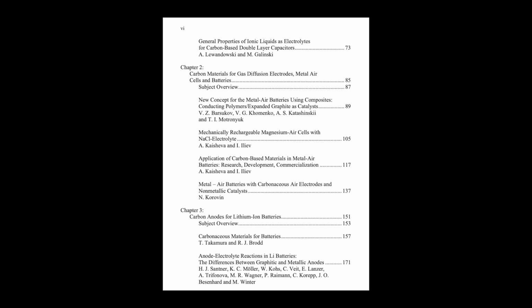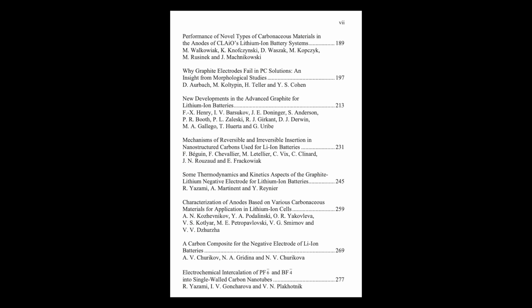The source also got really fundamental, looking at the actual steps of lithium going into graphite. Yeah, detailed studies looking at the staging process, how lithium fills the layers. They found some weird things, anomalies in how the dimensions changed, or the speed of the reaction, or even the thermodynamics, especially during certain stage transitions. What caused those? They speculated it could be due to disorder in the graphite, internal stresses, the influence of the SEI layer, or maybe even temporary intermediate structures forming. It shows just how complex that intercalation process really is.